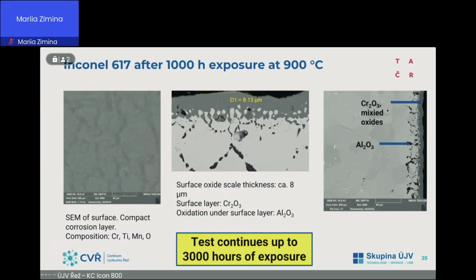Also, I'm very grateful to Jan Procházka, who spent dozens of hours with us analyzing oxide layers. Here we have results after 1,000 hours exposure at 900 Celsius. On the first SEM image of the surface, we found a pretty nice compact corrosion layer. It contained mainly chromium and oxygen, and a small amount of titanium and manganese. On the second and third cross-section images, the surface layer is formed from chromium oxide, and the oxidation under the surface layer is formed from aluminum oxide.